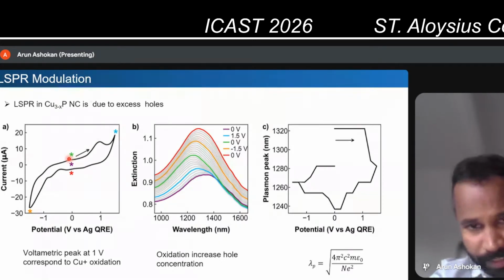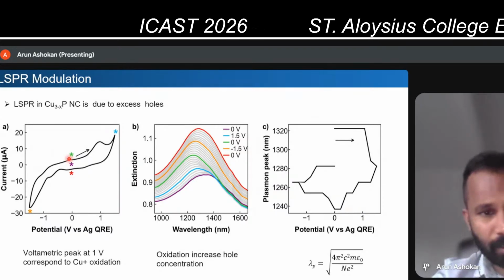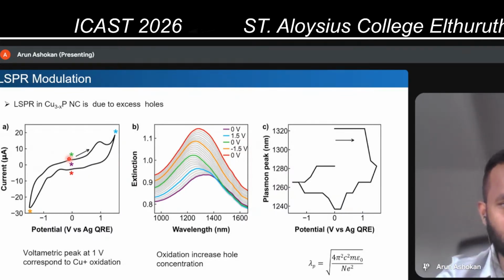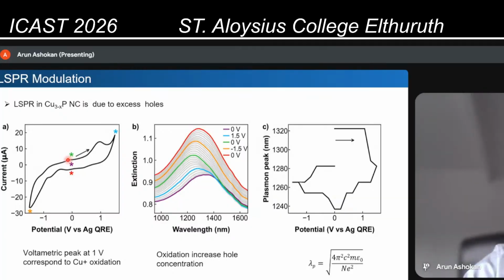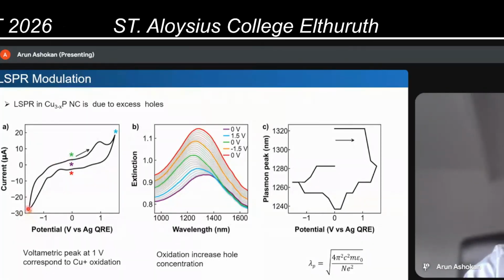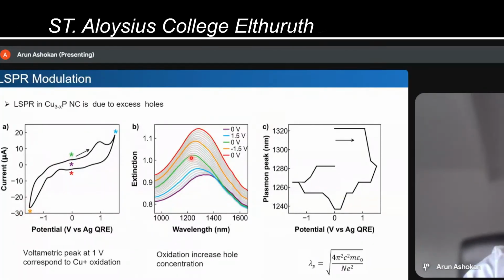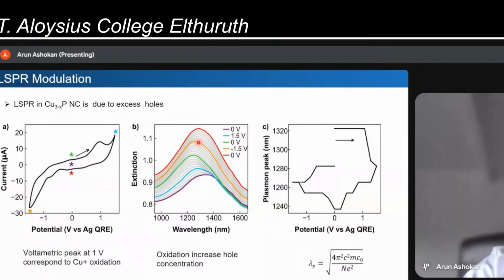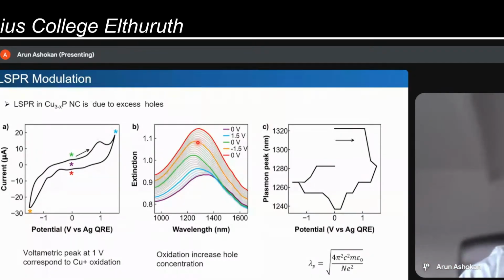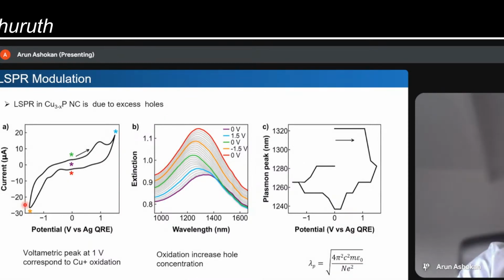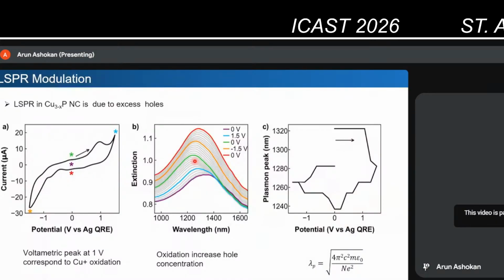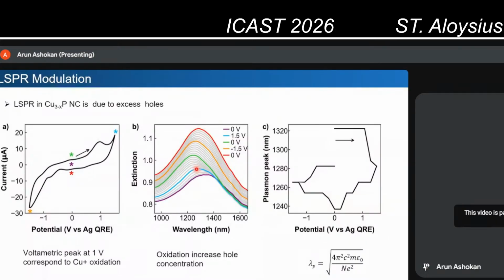We are going to the negative potential where we are injecting electrons. So we are reducing the number of holes. So what happens is we are going up to minus 1.5. That's the orange. You can see that it's started redshifting again. So you are reducing the concentration of holes when you are reducing the nanocrystals. And when you switch back to 0 volt, it's still redshifted and almost came back to the original, not exactly, but there is a slight difference because of the scanning rate.